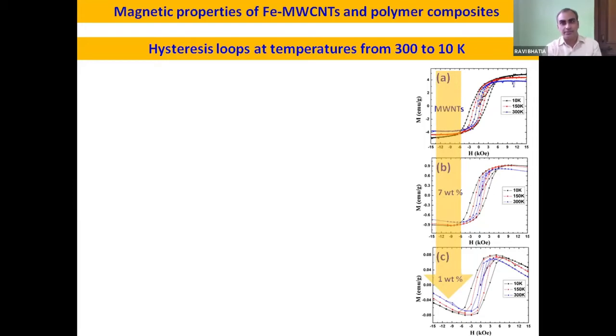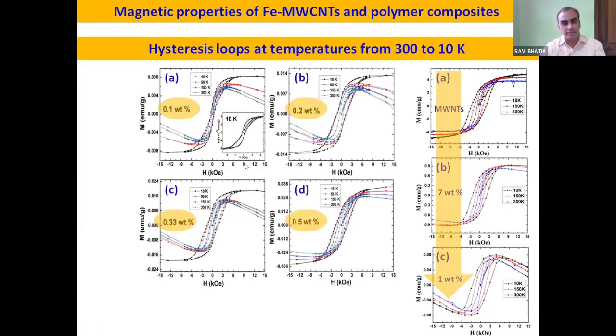So we had done a very systematic study on this particular sample. We studied the bulk sample of a multi-wall carbon nanotube, and then we went to 7 weight percent sample, 1 weight percent sample, 0.5, 0.33, 0.2, and 0.1. So we studied almost 7 samples for their magnetic properties.